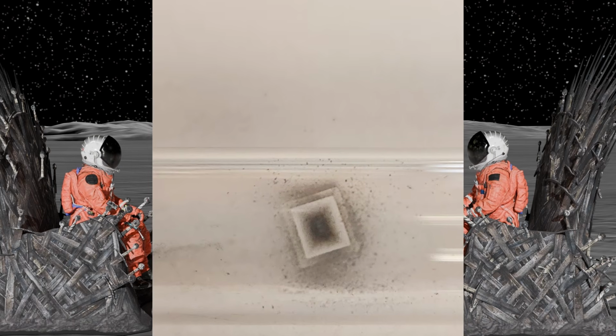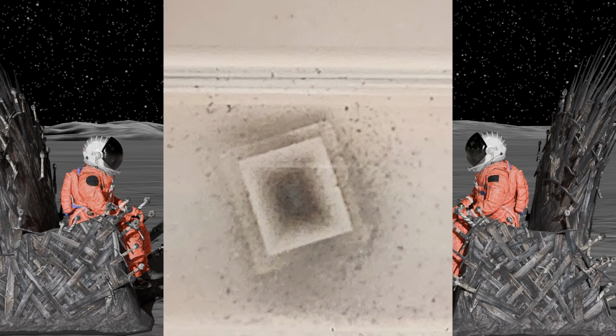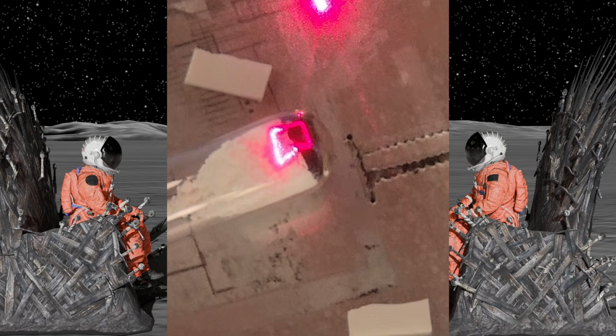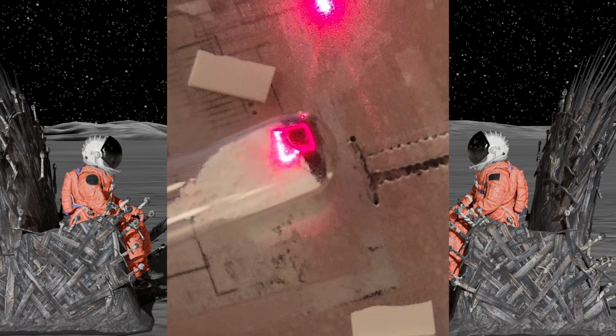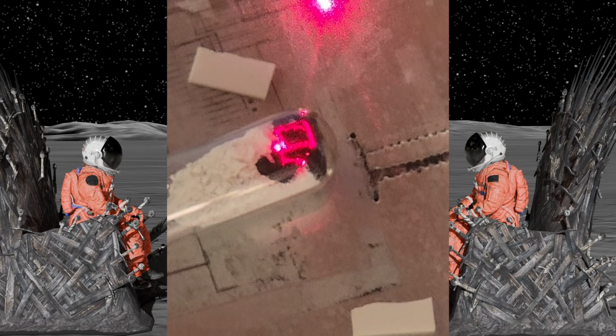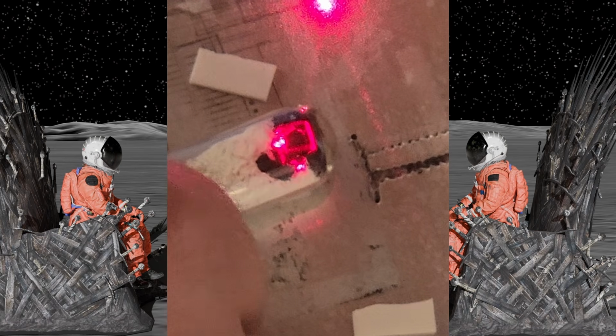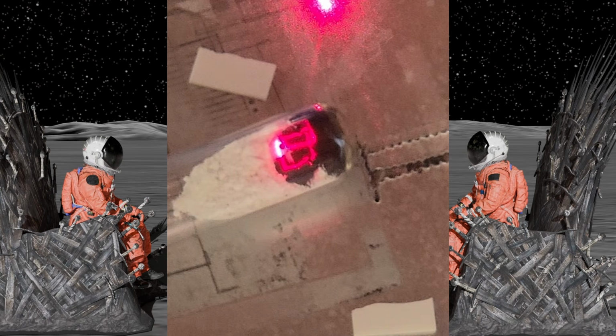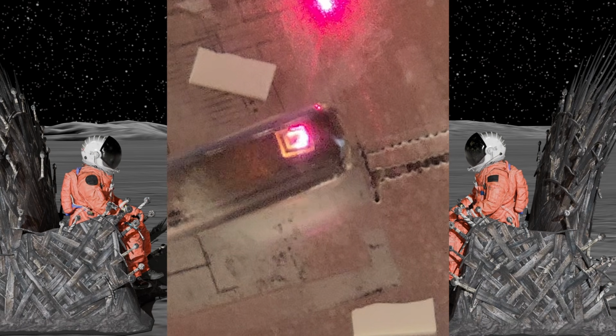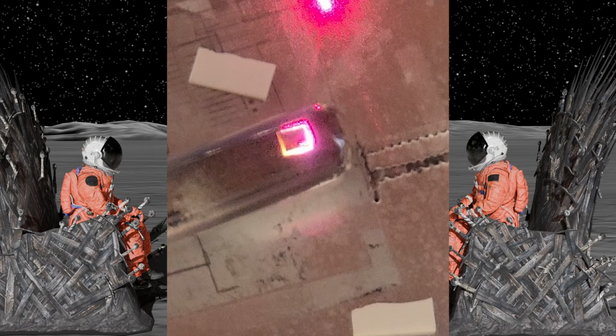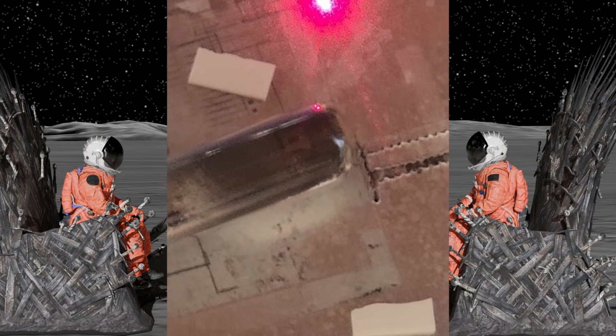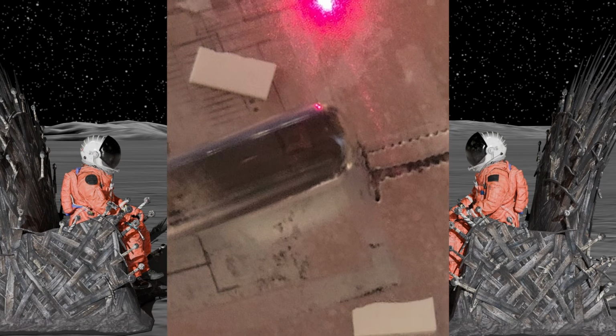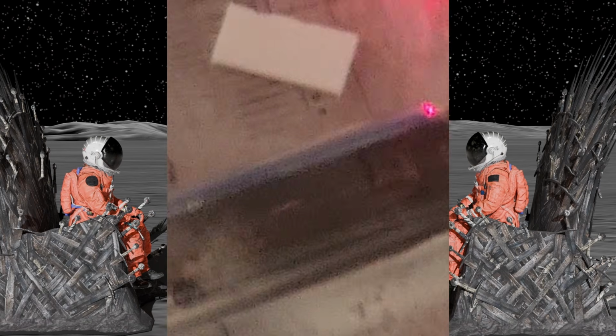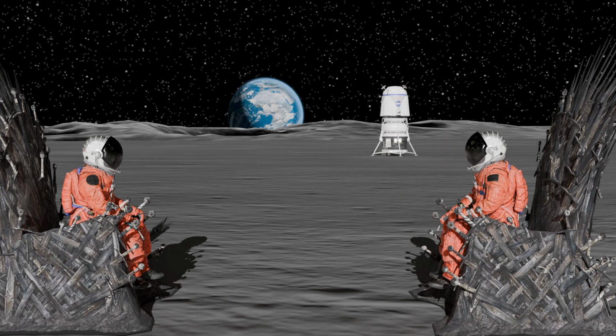However, we did show that we were able to get some titanium reduction with some conductivity on other samples. It's a little bit more difficult when they were intimately combined because of the nature of the two colors. One is extremely dark. We were using pure oxides, so a lot darker than you would have on the moon. And then the other one was bright white. So in showing this, that it's possible, it just needs to be fine-tuned. So it's possible to have mixed oxides and then to selectively sublimate them with this laser. And that's incredible because you got the settings from the oxides and then you mix the oxides together. You didn't do all of them, but you did multiple of them, and you were able to get selective sublimation even though they're together.